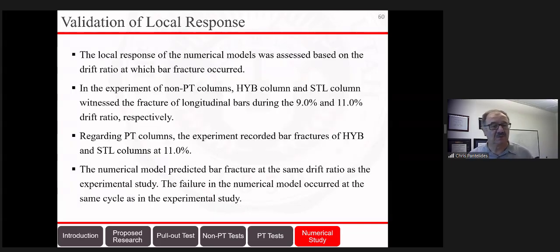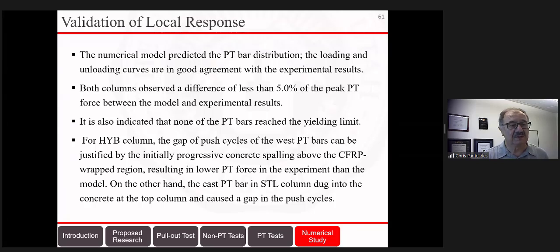The local response was based on the drift. It was within fractions, let's say 10%. And we reached the 9% and 11% that we saw in the test. And the bar fracture was predicted in the same drift ratio as the experiment. So we feel confident about this.